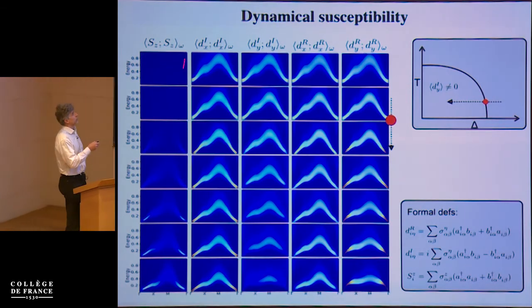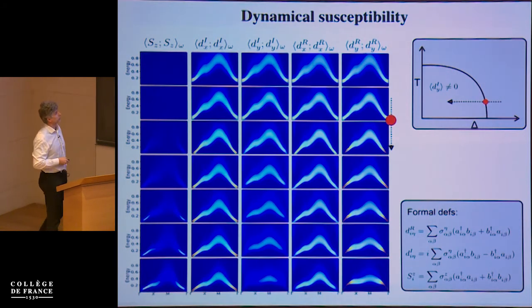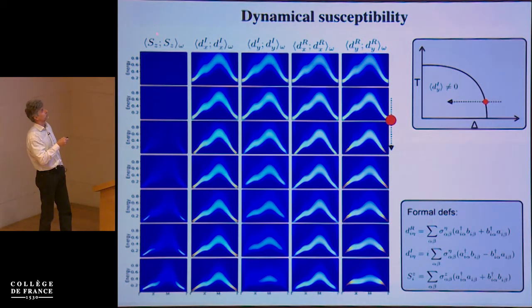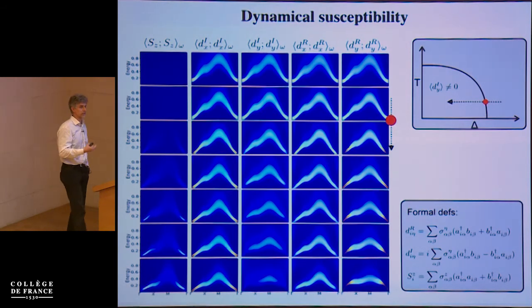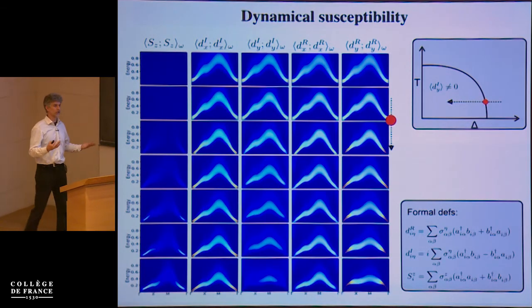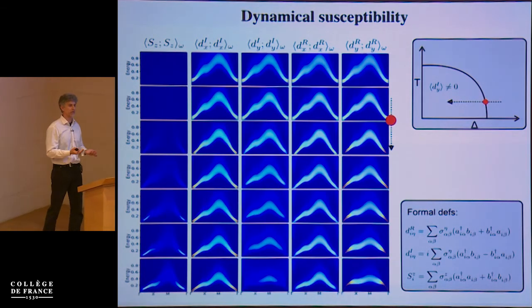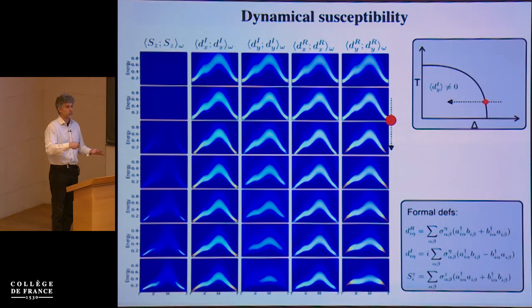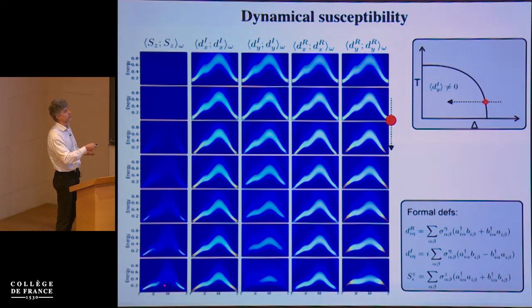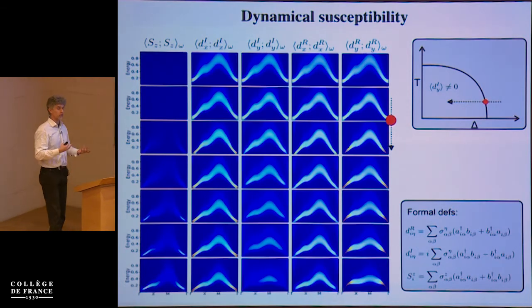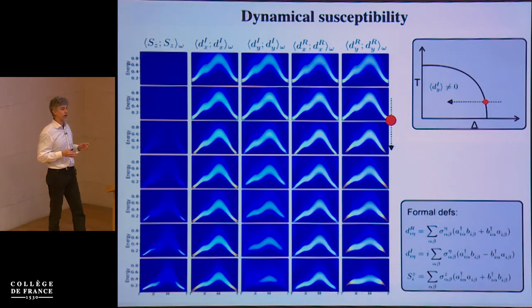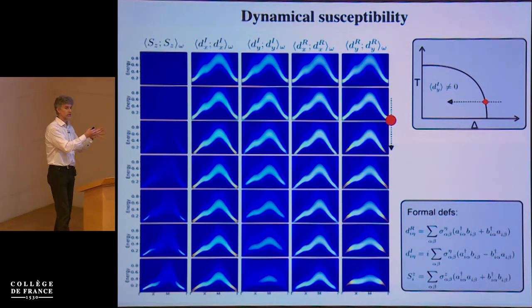One interesting observation, which I'll comment on more later, is the evolution of this dynamical spin structure factor. In the normal phase, there is absolutely no response—no surprise, since we essentially have a band insulator with no moments to flip. But when we go to the ordered phase, there is clearly a well-defined dispersive feature which looks like a spin wave, yet there are no ordered moments in this system.